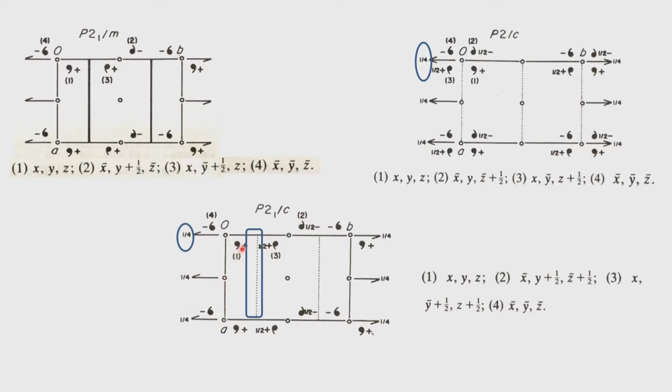So the symmetry operation 1 therefore will take this position 1 to a mirror position and then half translation. So this half translation will generate this point 2, which is half minus. Okay, that means it is below. So what would be the equivalent point? If there was only a 2-1 screw axis, the equivalent points would have been x bar, half plus y, z bar.